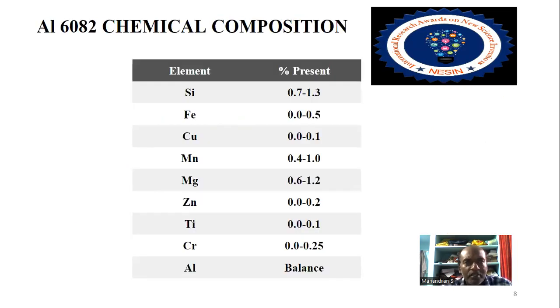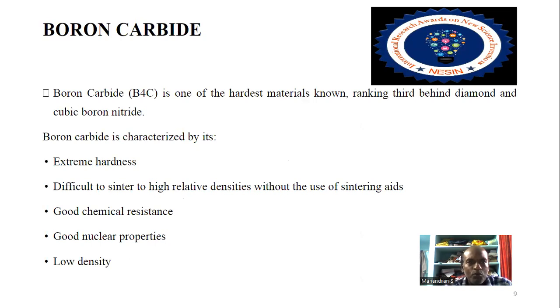This is the aluminum 6082 chemical composition. There is silicon 0.7 to 1.3 percent, iron 0.0 to 0.5 percent, copper 0.0 to 0.1 percent, manganese 0.4 to 1 percent, magnesium 0.6 to 1.2 percent, and chromium 0.0 to 0.25 percent. The remaining is aluminum, and this is the aluminum 6082 chemical composition. Next one is boron carbide.